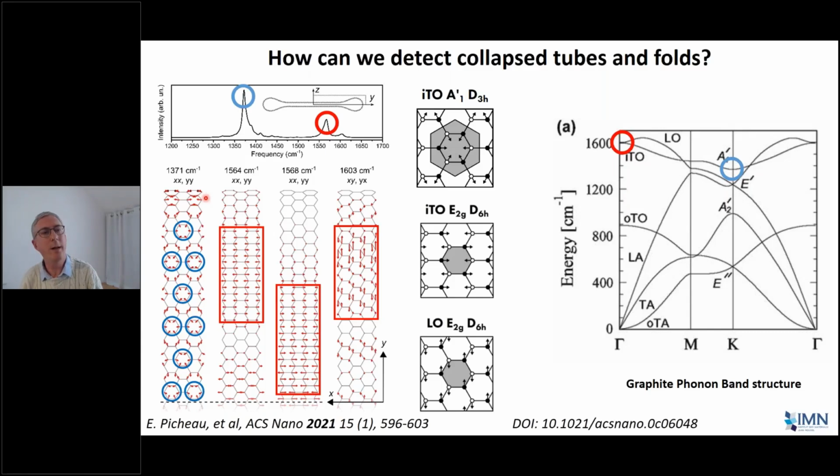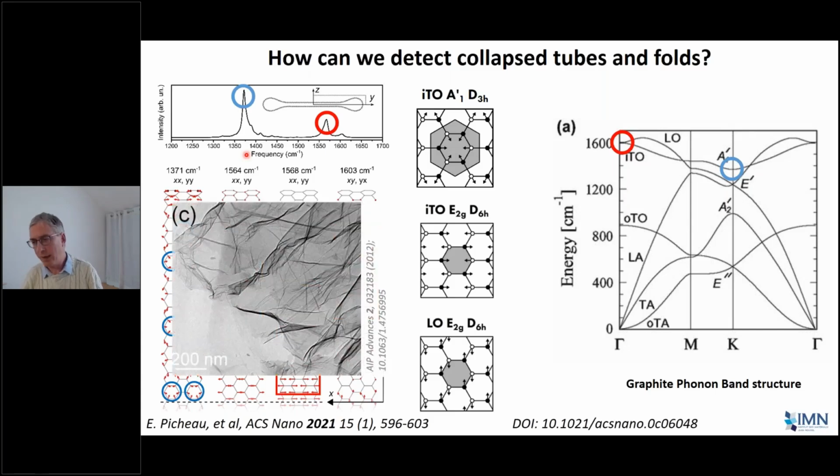As soon as you fold it, this peak comes up very, very strongly in the measurement, in the calculations. So something you should be aware of if you're working in graphene and, for example, you're separating sheets out and your separated sheets have a big D peak, it might not be that they're riddled with damage and your method is very poor. It might just be that they're very crumpled up, so they have a lot of folds. If the D peak is intense and very sharp, that's probably what's going on. So it's probably good news for people developing new ways of making graphene sheets.